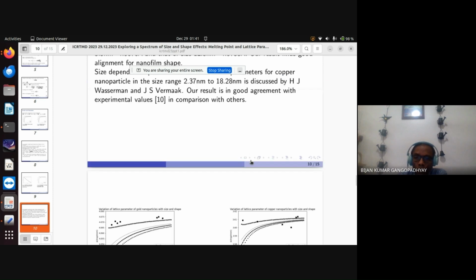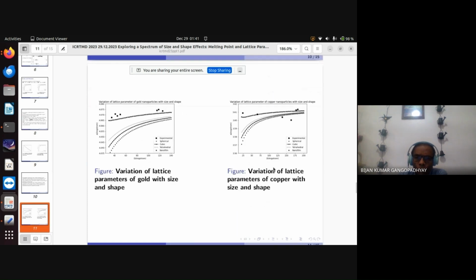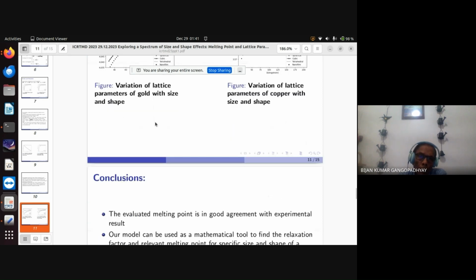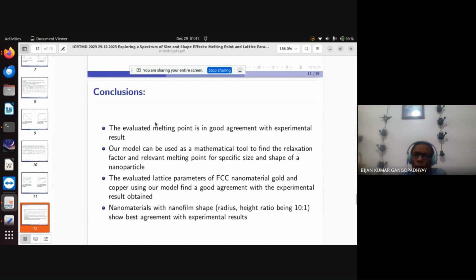It's an interesting one. This is the figure drawn for gold and copper separately. So this is experimental, and this is for spherical, this is for cubical, this is for tetrahedral, but this is for nanofilm. So nanofilm shows almost the experimental result, and this finds better agreement than the other ones. So that is my approach. So as far as the calculation is concerned, the evaluated melting point is in good agreement with the experimental result. So our model can be used as a mathematical tool to find the relaxation factor and relevant melting point for a specific size and shape. And similarly for the next parameter, we find good agreement, and in fact the nanomaterials with the nanofilm shape show this agreement with the result.